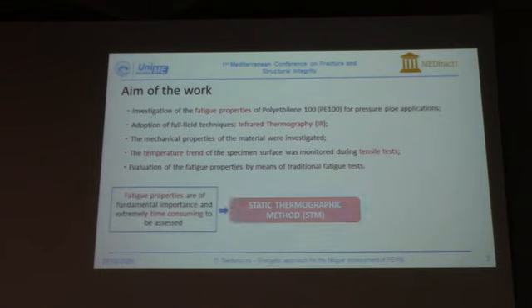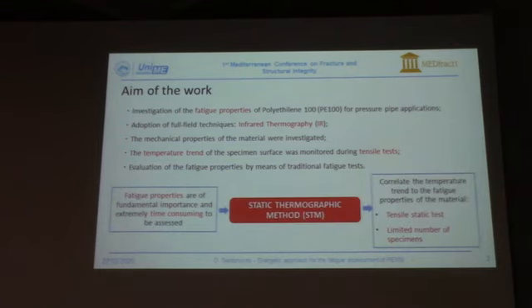But the real point is that the fatigue properties are of fundamental importance, but on the other hand they are extremely time consuming. So in this work the authors propose the static thermographic method as a rapid procedure to determine the fatigue limit of materials, adopting a limited number of specimens and monitoring the temperature during a static tensile test.